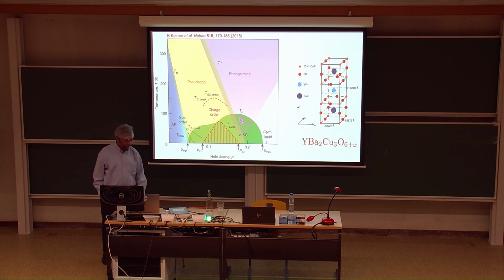And here's the antiferromagnet I already mentioned. This is when P is close to 0, you get the antiferromagnet. And when the antiferromagnetism disappears, eventually it's replaced by superconductivity. But at low temperatures, many other things also happen, depending on which compound you use, depending on whether you apply a magnetic field to suppress the superconductivity or not. You can also get various charge density wave orders appearing.